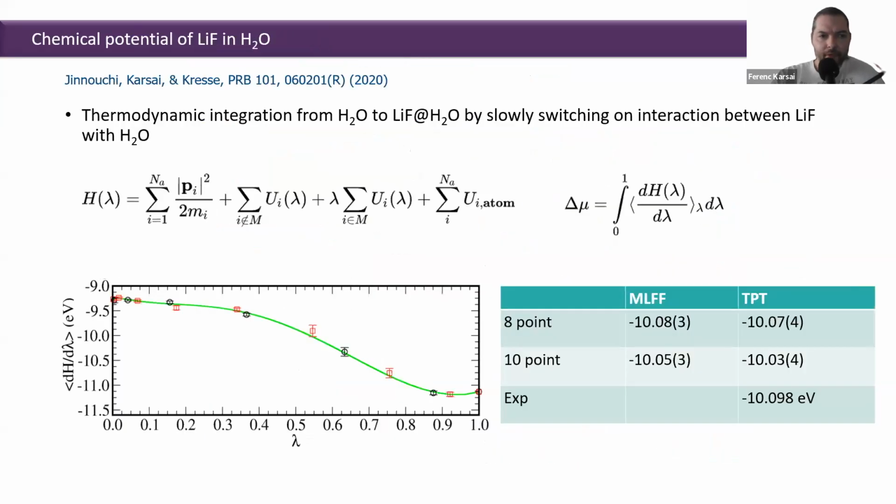Another paper I wanted to show you here is the calculation of the chemical potential of lithium fluoride in H2O. For that, we used a specifically modified version of thermodynamic integration, specifically designed to use with force fields, where we can turn off the atomic potential energies for a given atom with a coupling parameter lambda.